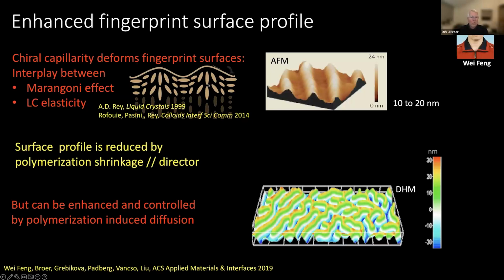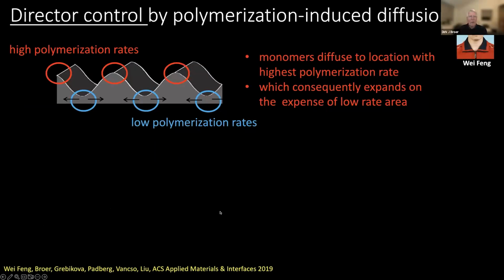So this is reducing this effect, but it can be enhanced again by controlled polymerization-induced diffusion. Let me try to explain this here. So if you have a film and you have locally differences in polymerization rate, then you will have diffusion of your reactive agents to the area where the polymerization rate is the highest, which means if we have here the highest polymerization rate, this will become larger and here it will reduce in thickness.